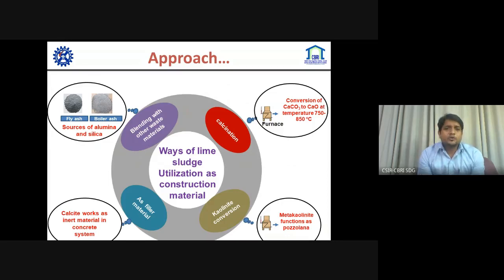In this approach, we can use lime sludge in different ways, like blending with other waste materials. We can blend the lime sludge with fly ash and boiler ash because they are sources of alumina and silica. So we can blend this calcium with alumina and silica, which can make a better construction material. Another is calcination, calcium carbonate to calcium oxide, but it is again a very energy intensive process. Third, we can use it as a filler in concrete. Raw lime sludge is an inactive material, it's calcium carbonate, and it will not do anything in the concrete system. So we can use it as a filler, but the utilization of lime sludge as a filler will be very minimal.